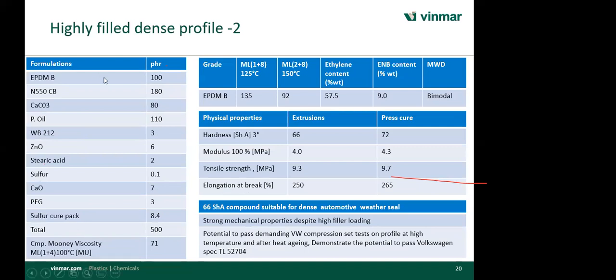See here, I have taken EPDM B. The property of EPDM B is Mooney 135 at 1+8 at 125 degrees centigrade. Ethylene is 57.5, ENB is 9, and it's a bimodal grade. And here we have considered a loading of 180 PHR carbon black and 80 PHR calcium carbonate. So total PHR becomes 500.